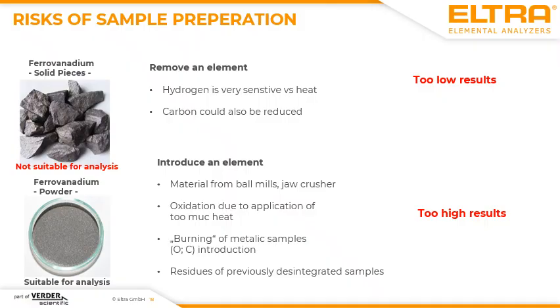But please consider that the preparation processes could falsify the results, because there are two tendencies. On the one hand, you can remove an element, or you can introduce an element. Removing an element is typically something which is done for hydrogen analysis, because the element hydrogen is very sensitive to heat, because it will leave the sample very fast. The other thing is also carbon, for example. When you introduce too much heat, you can maybe cause an oxidation process,